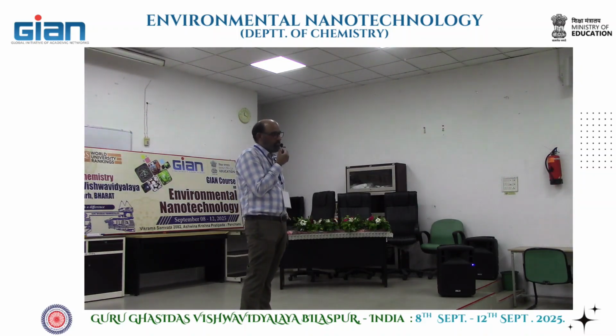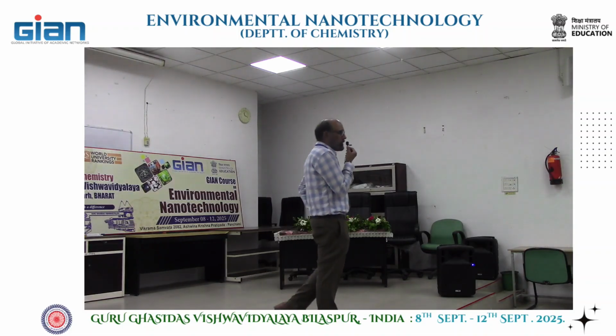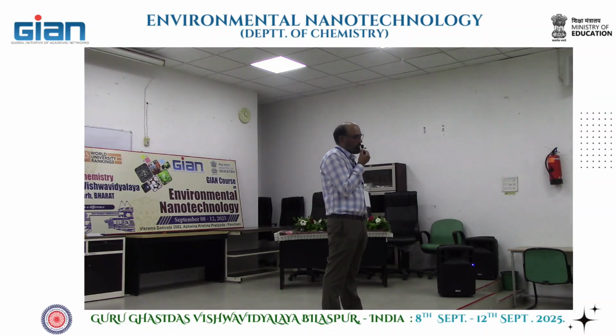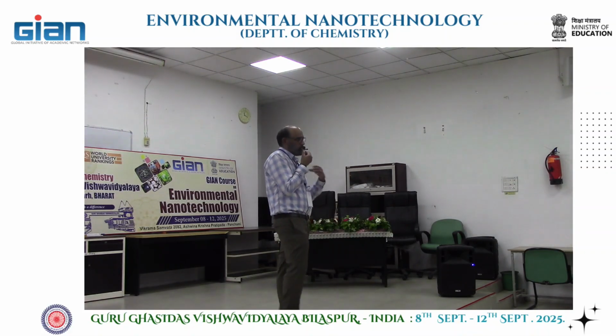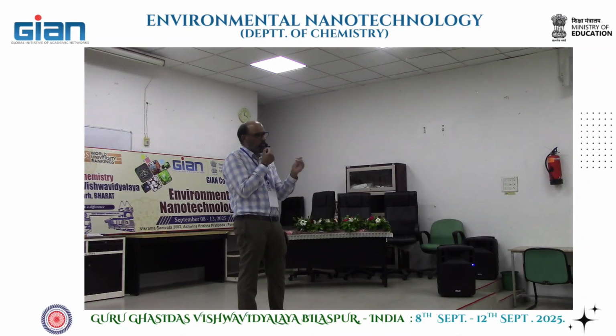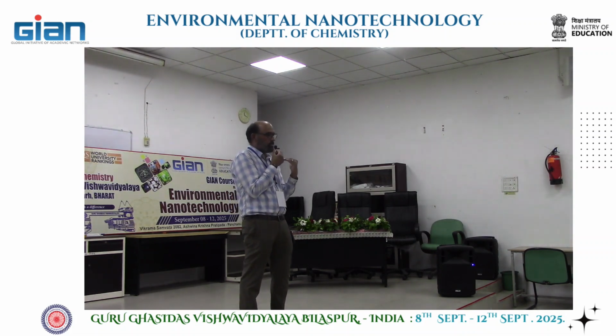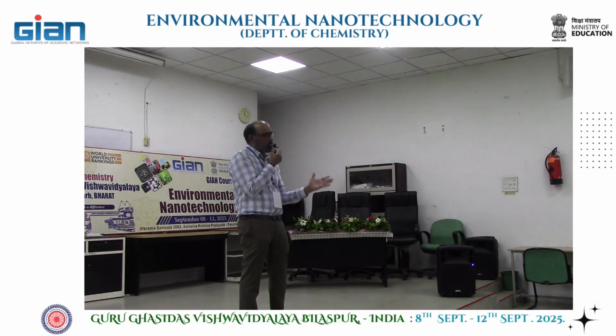When you take the example of your system, you have used this PVP and cellulose acetate. Have you characterized the cellulose acetate? We commercially purchased it and then used it, and after the film is formed, from that we removed the acetate to make it hydrophilic. No, partly it's remaining. 100% is not possible to remove, and we don't need that much because we just wanted the hydrophobic to hydrophilic transition. So we are not concerned about how much percentage of cellulose acetate is remaining. We are concerned about how much the contact angle is changing.